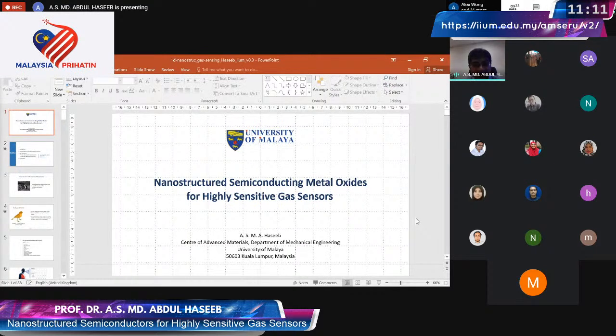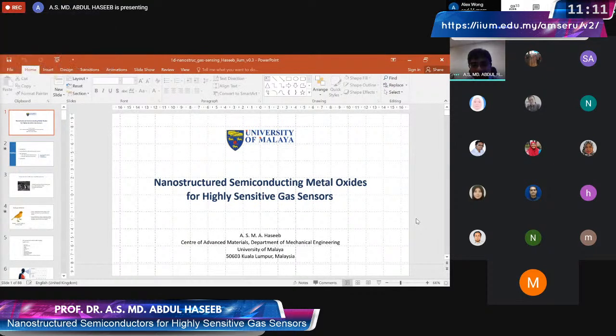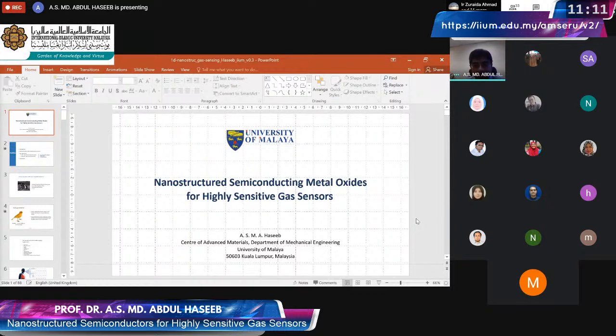Does the presence of vanadium affect the material? We also wanted to see the effect of other alloying elements. What we found is that the vanadium does not take part in any process. It remains inside the oxide and the particle. It does not come up to the surface, because everything that happens here is on the surface. So if it does not segregate selectively to the surface, it does not take part in the nanostructure formation. What's the percentage of vanadium in Ti64? The vanadium was 4%, and aluminum 6%.